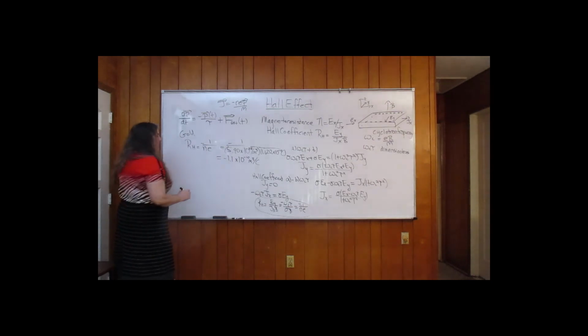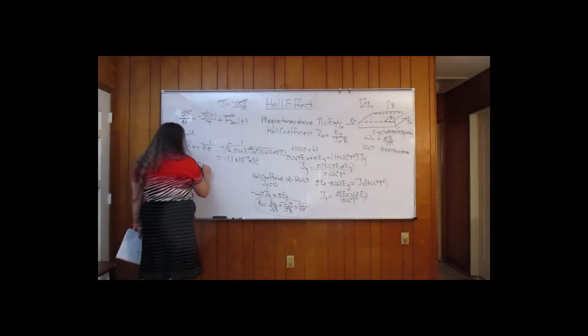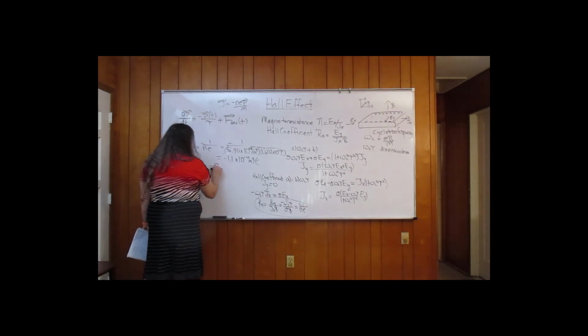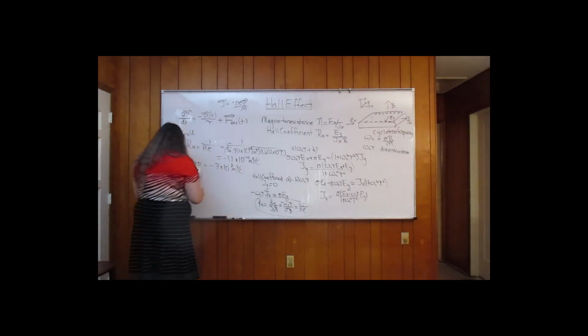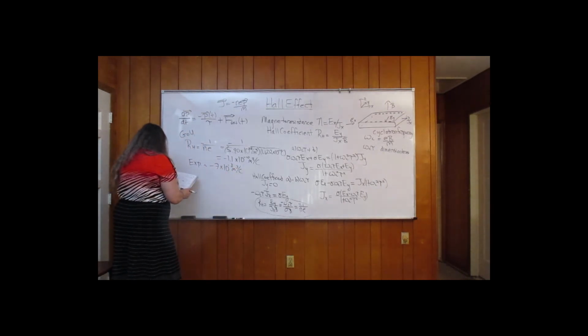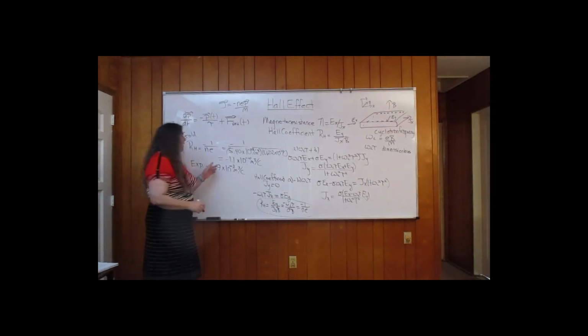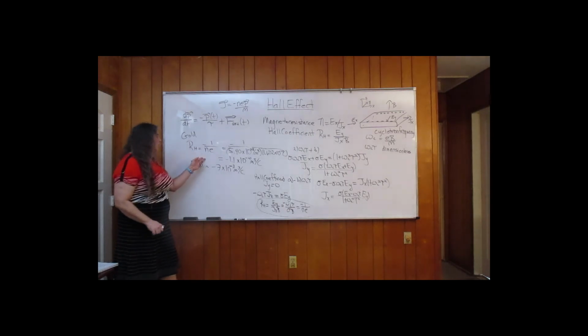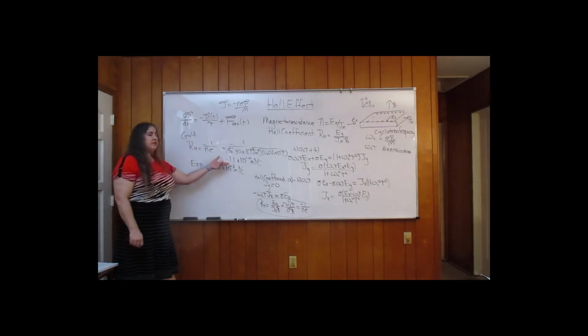So how good a value is that? Well, experimental values are around -7 times 10 to the minus 11th cubic meters per coulomb. There's not very good agreement between the calculated Hall coefficient and the experimental accepted value. At least it's in the right ballpark.